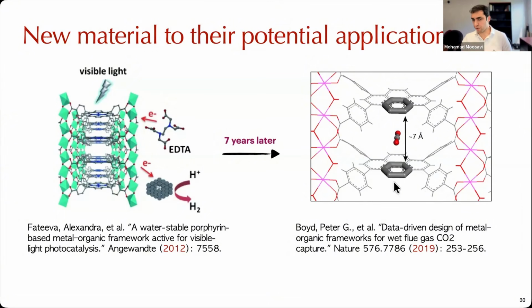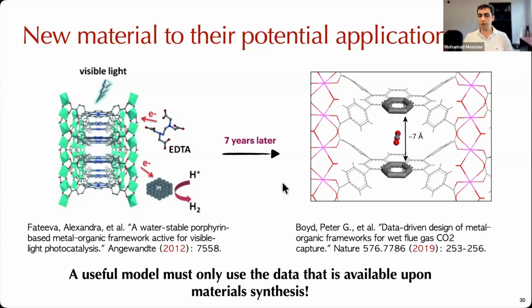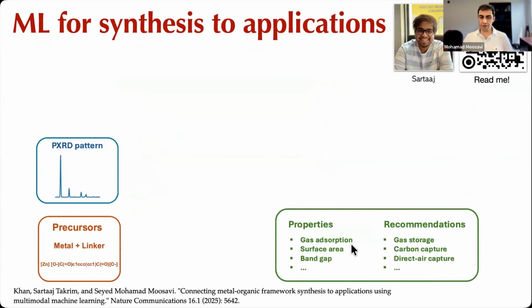To make a useful model that can recommend applications, we needed to make a model that only takes data that is available upon synthesis of the material, not necessarily the clean crystal structure or fancy machine learning methods, simply data that is available upon synthesis. In our field, this is basically the precursors that are used for synthesizing the material and the PXRD pattern. The PXRD pattern just proves that the material is crystalline and it is formed. As soon as you have these two, you can say the MOF is formed.